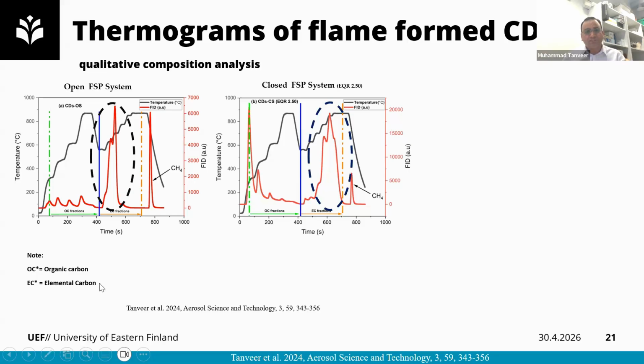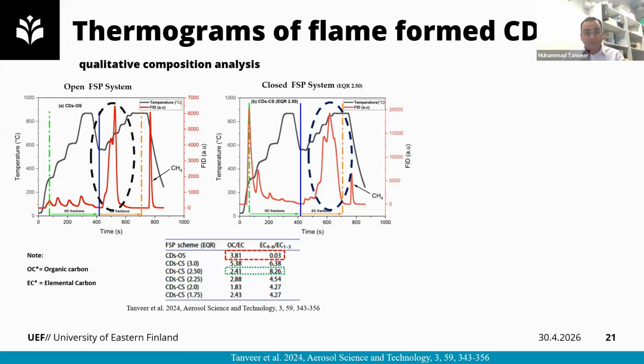This shows elemental carbon. Overall, carbon dots are composed of organic carbon and elemental carbon. So these structures basically define the overall composition of the carbon dots, and then tune the properties of these carbon nanostructures. You can see here for the open system, the organic carbon to elemental carbon ratio is quite high, but in the case of the higher EQR value, this can be quite lower.